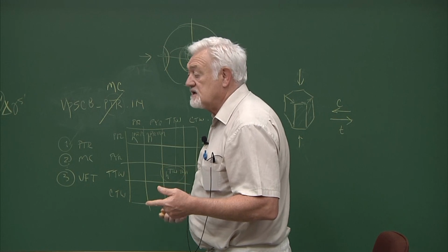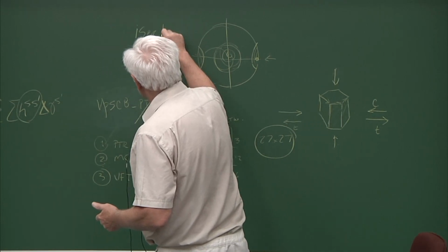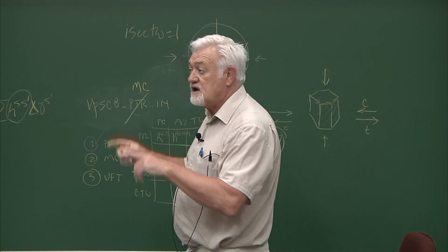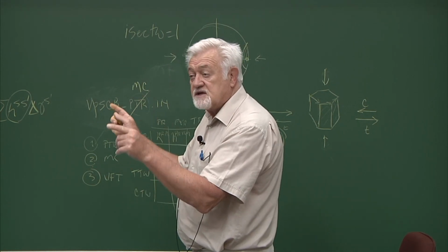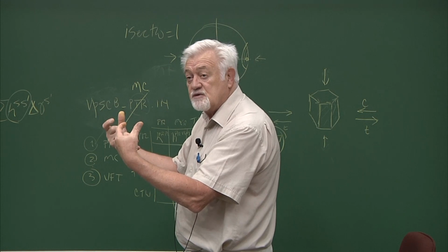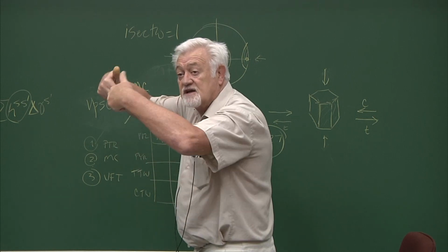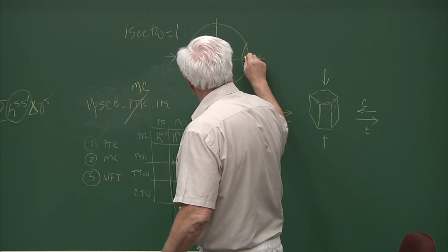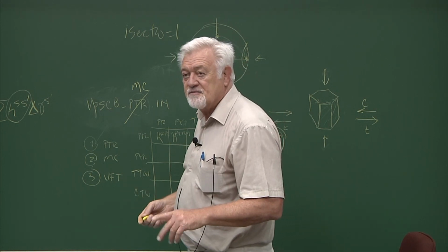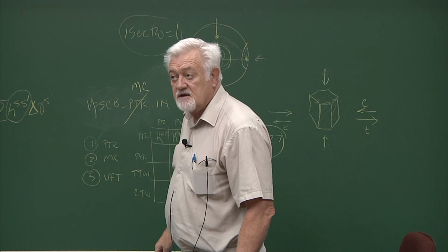So do you remember that I talked about I-secondary twinning equal 1? If you allow for secondary twinning, what you do is you allow for a fraction of the material that has twinned, you have created a new grain that is the twin grain. But if you are allowing for secondary twinning, then that grain is going to twin again and bring this somewhere here, more or less. So that is one of the effects of allowing for this I-secondary twinning there.